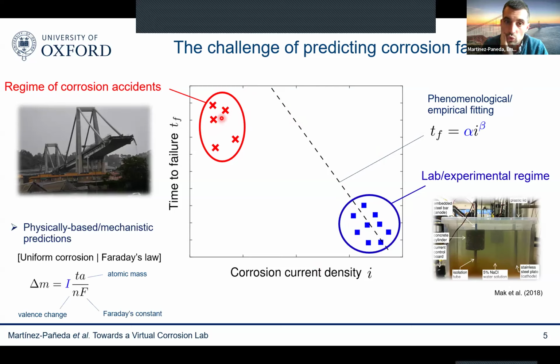We do have, to a certain extent... maybe the best thing to say is that what we want at the end of the day is to replace these empirical data fitting models with physically based mechanistic predictions. And we do have one model in corrosion that is physically based and works very well. It is only valid for uniform corrosion. This is what's called Faraday's second law for corrosion.